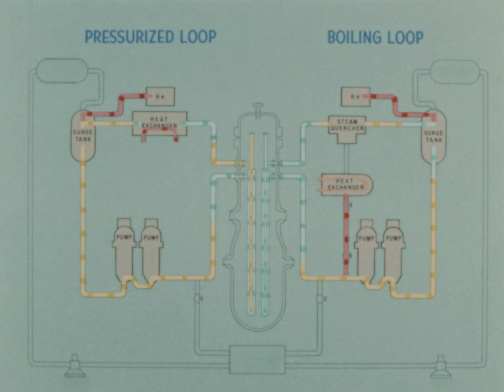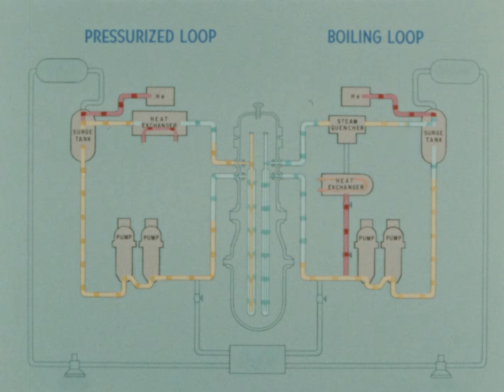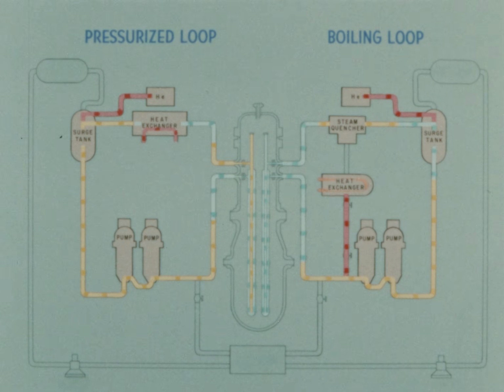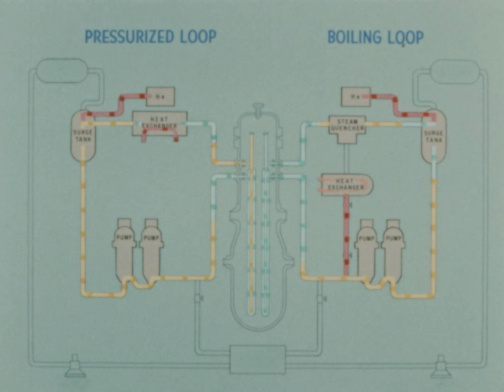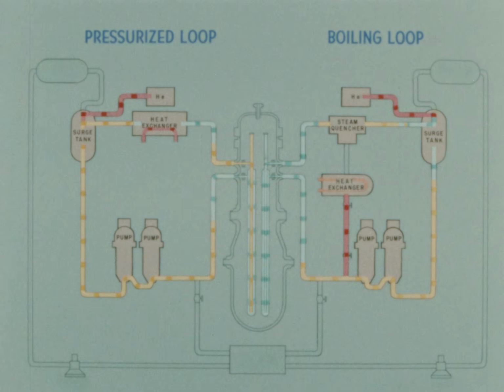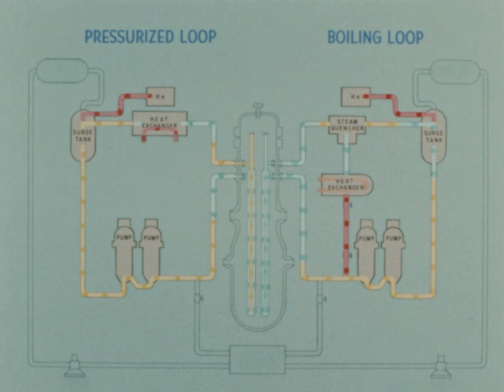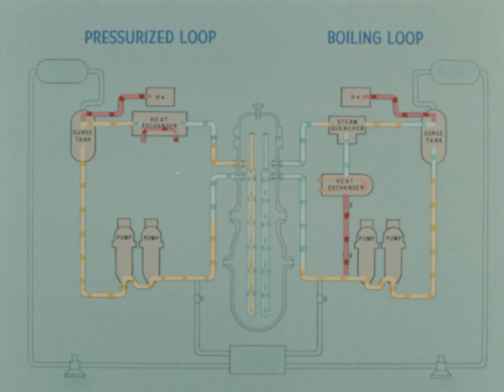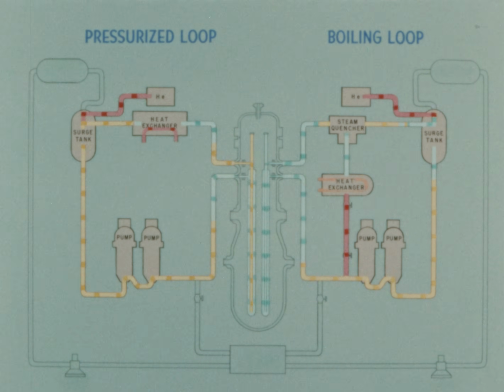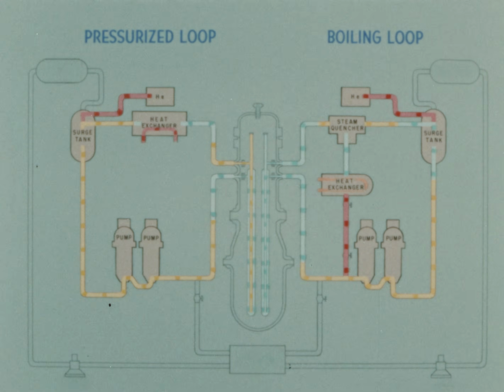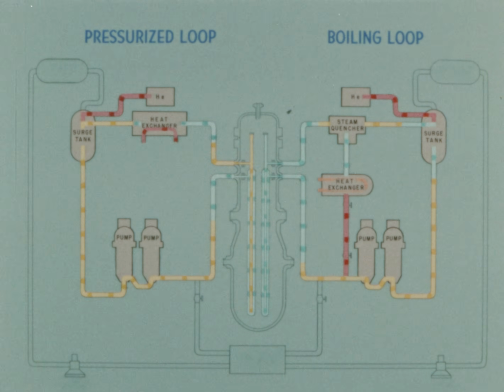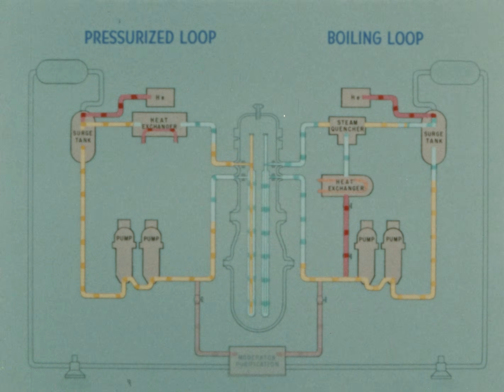Cooling is provided by a bypass of the pump discharge, which goes through a cooler similar to the liquid loop cooler. The cooled D2O is then used to quench the vapor from the outlet of the loop tube. Control is guided by the temperature differential across the steam quencher. The outlet steam quality is adjusted by the bypass rate through the cooler.